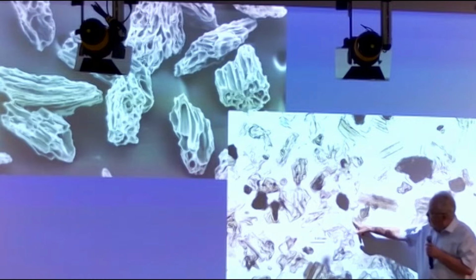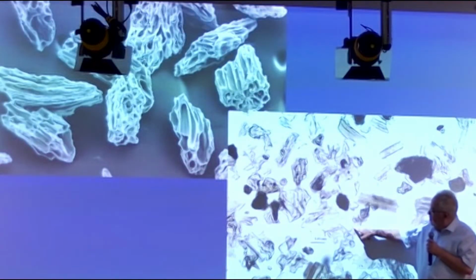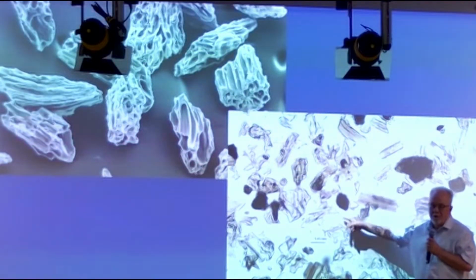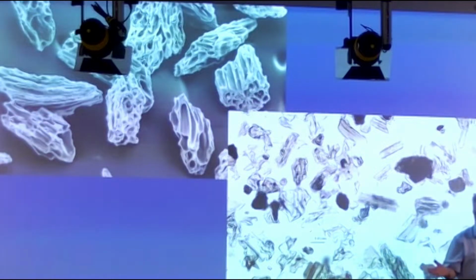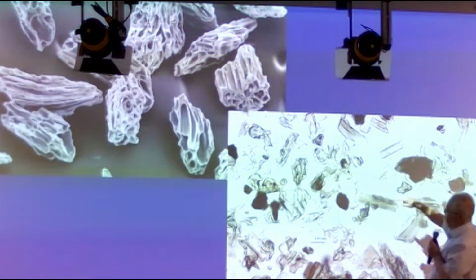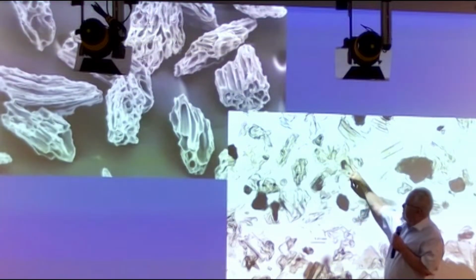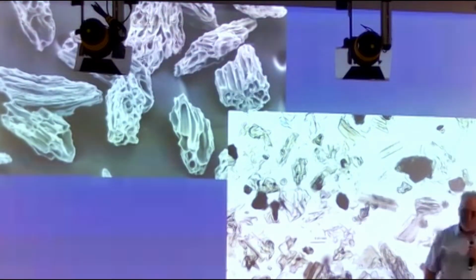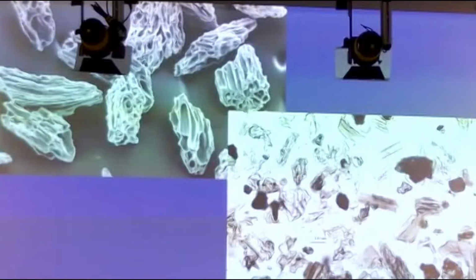But we also get these funny looking things that don't look like crystals. They're absolutely transparent. They have no crystallographic form. They're amorphous. They're without structure. That's the glass. And so you have a mixture of glass and crystals, more or less. And you also have bubbles inside of some of the glass. And over there you see a scanning electron microscope shot of fine pyroclasts, and you see